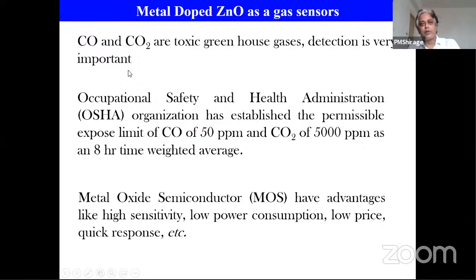So we have a lot of pollution in the environment. In order to detect that, we have to detect CO and CO2. These are important greenhouse gases, and in order to detect them, it is very important to have a sensitive and selective sensor. According to the Occupational Safety and Health Administration, OSHA, the permissible exposure limit of CO is about 50 parts per million and of CO2 is 5,000 parts per million, as an 8-hour time weighted average. If we are exposed to more than this 50 parts per million of CO or 5,000 parts per million of CO2, then that is not good for health. It will seriously damage our nervous system or other parts of the body, and can produce cancer or tumors. So it's very important to detect these toxic gases.